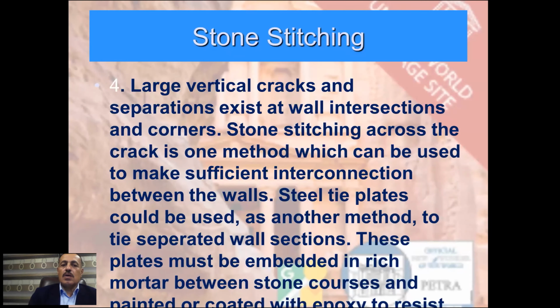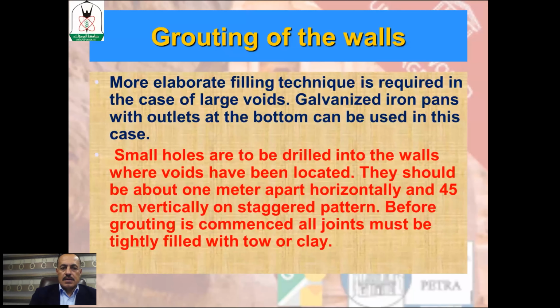Stone stitching is also another technique that we proposed. It can be used to make sufficient interconnection between the walls. Steel ties could also be used as another method to tie separated wall sections. A more elaborate filling technique is required in the case of large voids. Galvanized iron pans with outlets at the bottom can be used in this case.